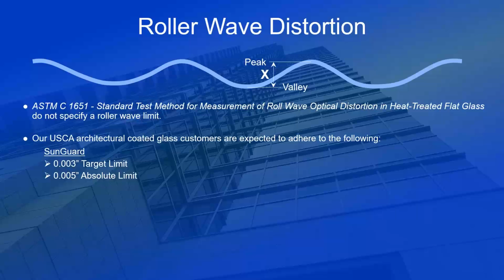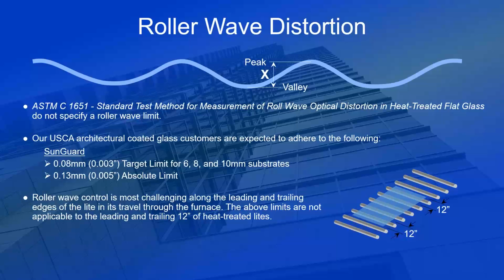So internally, we target limits of roughly 0.003 inches, 0.005 absolute inch limit. These equate to around 0.08 millimeters, 0.13 millimeters, and this is for commercial grade thicknesses of 6 millimeter, 8 millimeter, and 10 millimeter substrates, or quarter inch, 5/16, and 3/8. Now, the roller wave control along the leading and trailing edge is more difficult. And so this 0.003 or 0.005 target is relaxed at the leading and trailing edge, often to around 0.008 inches.